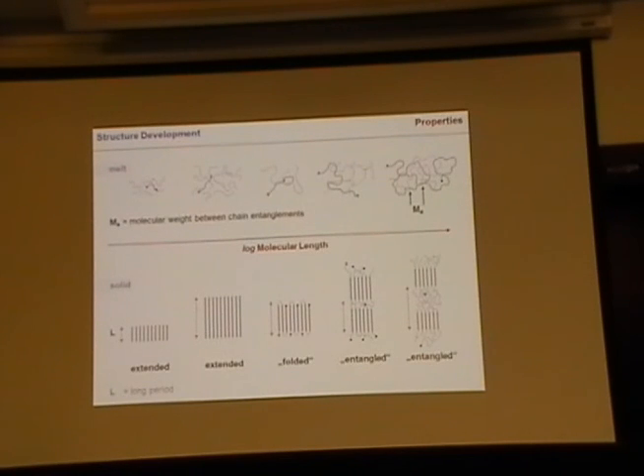To what extent is entanglement determined during the synthesis? Good question actually. Gore-Tex, so it's Teflon, is synthesized in such a way that there is zero entanglement. So therefore actually you can process it in a solid state. So the synthesis determines it a lot. The thing is obviously the more your polymer is dissolved when it's synthesized, the more entanglement you'll get.